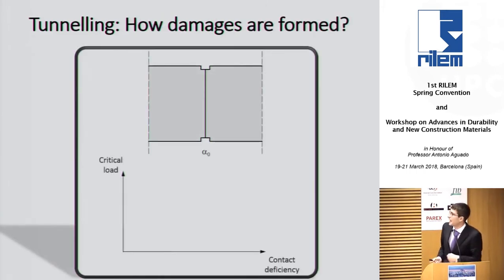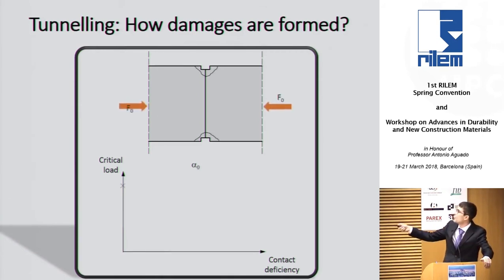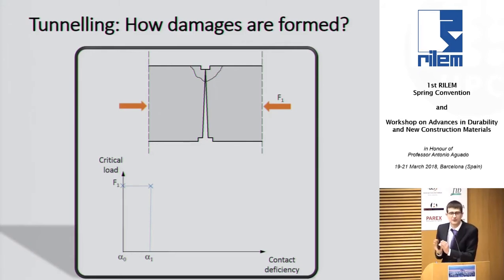So the philosophy behind it was, if we could simulate the behavior of a joint, we have here two segments in contact, and we apply a force, if there's no deficiency in contact between the segments, they will crack eventually. So we have a cracking load here. If you put a deficiency alpha 1 here and an angle, they're going to crack at a similar load because the deficiency in this case is very small.